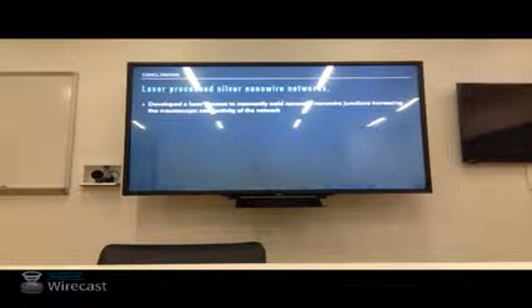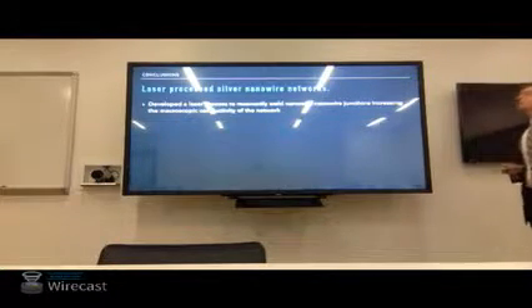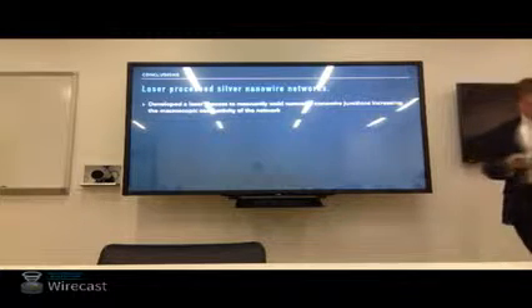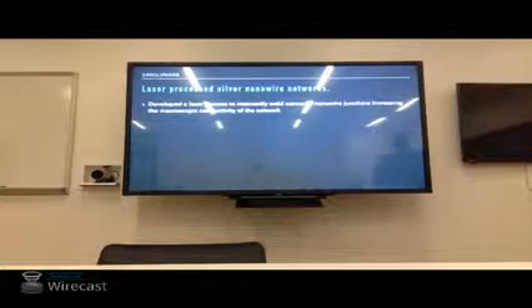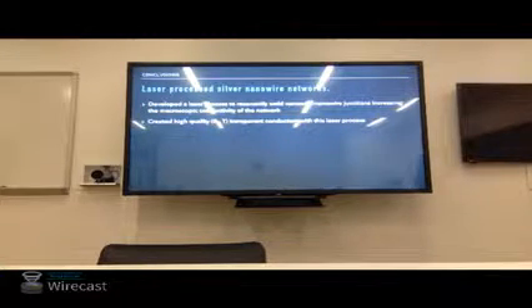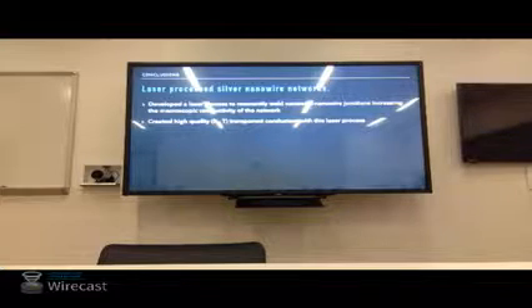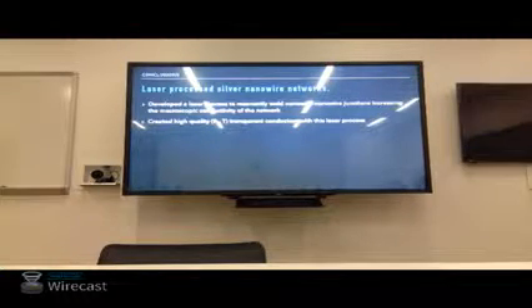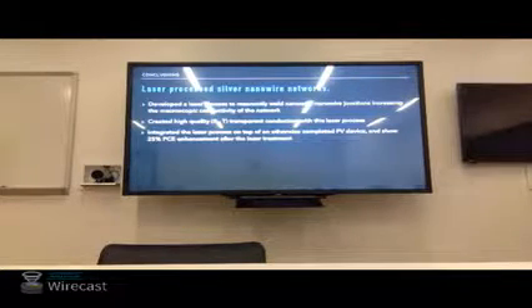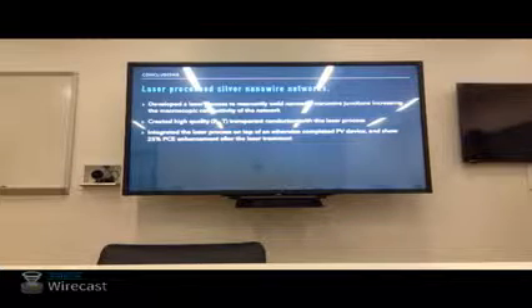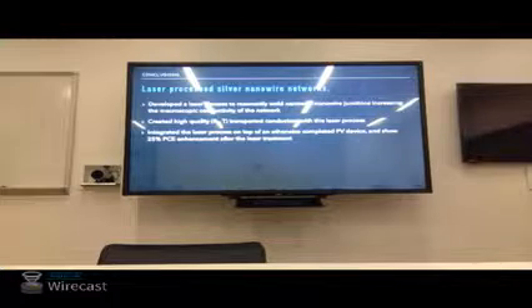So let me conclude by restating some of our main accomplishments. First, we developed the laser process to resonantly weld the nanowire-nanowire junctions, which drastically increases the conductivity of these transparent conductors. With this process, we made many very high quality, in terms of sheet resistance and transparency, nanowire networks. We've also integrated this process into the fabrication of a photovoltaic device on top of an otherwise completed device showing improvements to efficiency.